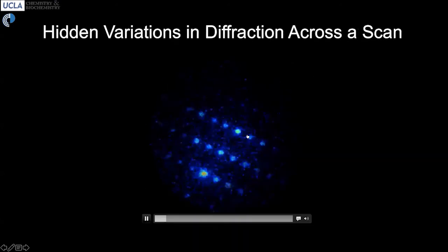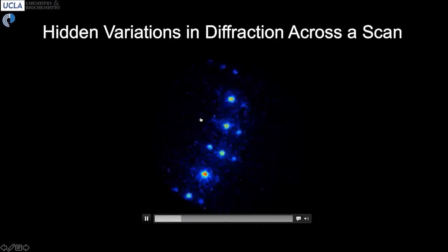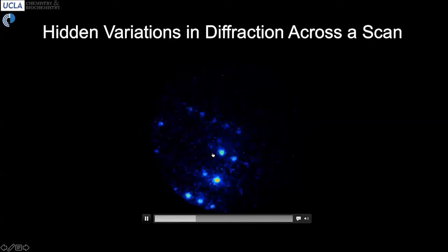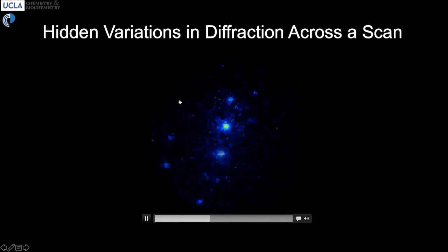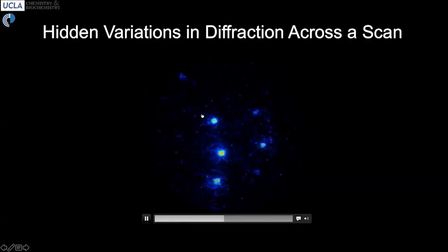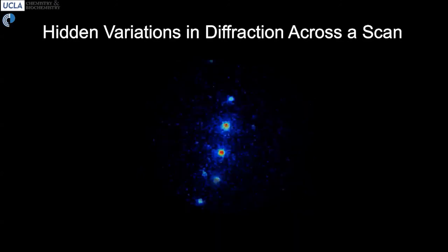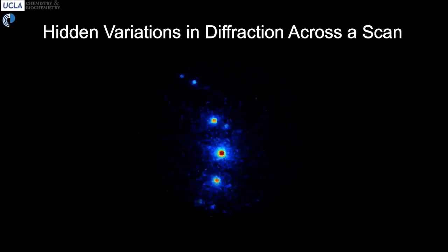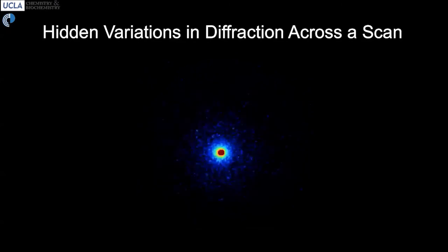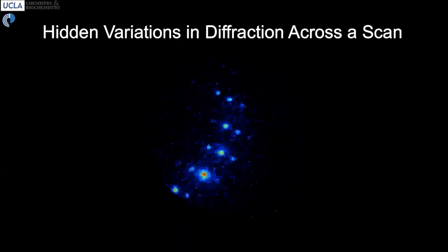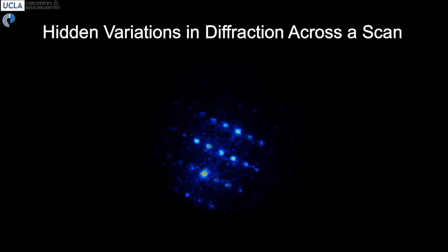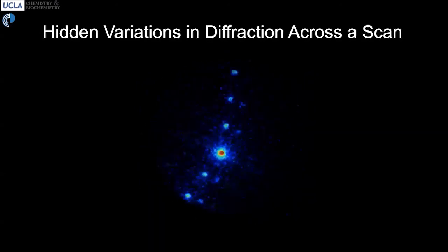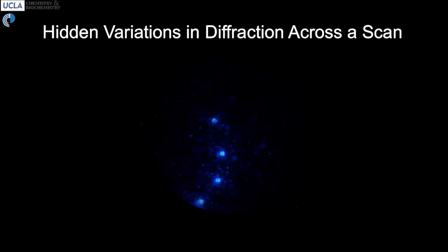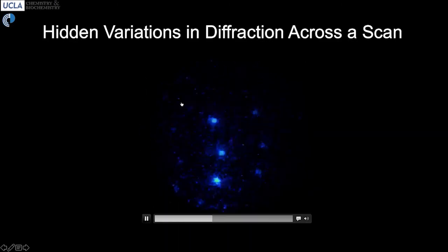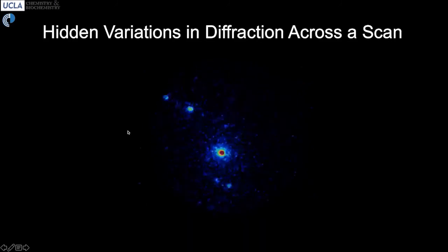Alternatively, we can look at individual diffraction patterns and not sum them up, but rather parse them out. And if you do this with a control sample, what you expect to see is an unchanging diffraction pattern, because if the sample is perfect, the lattice is perfect, no matter where you illuminate that lattice, you'll see the same diffraction pattern, the same type of interference between the lattice and the illuminated beam. And what we saw, even with the control sample in this case, which we thought was really pristine and regular, was quite a bit of variability when we did this experiment at Berkeley Lab.